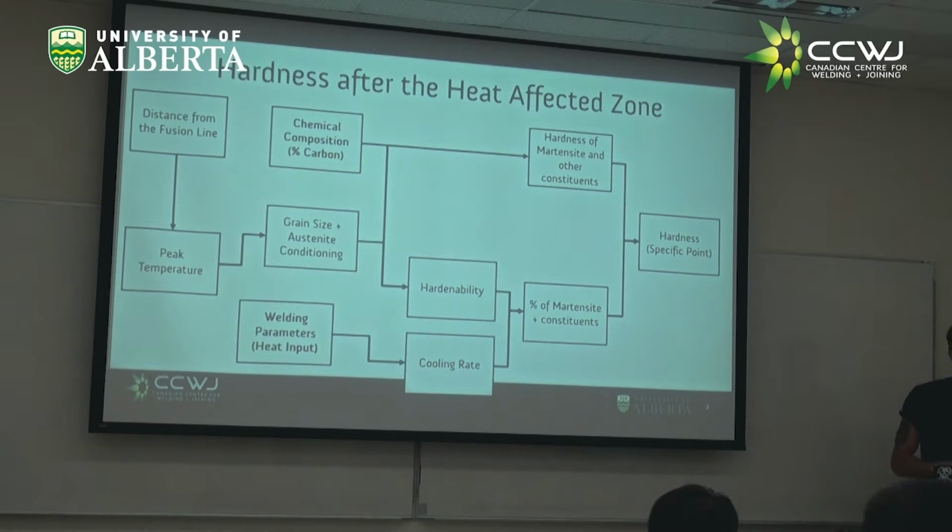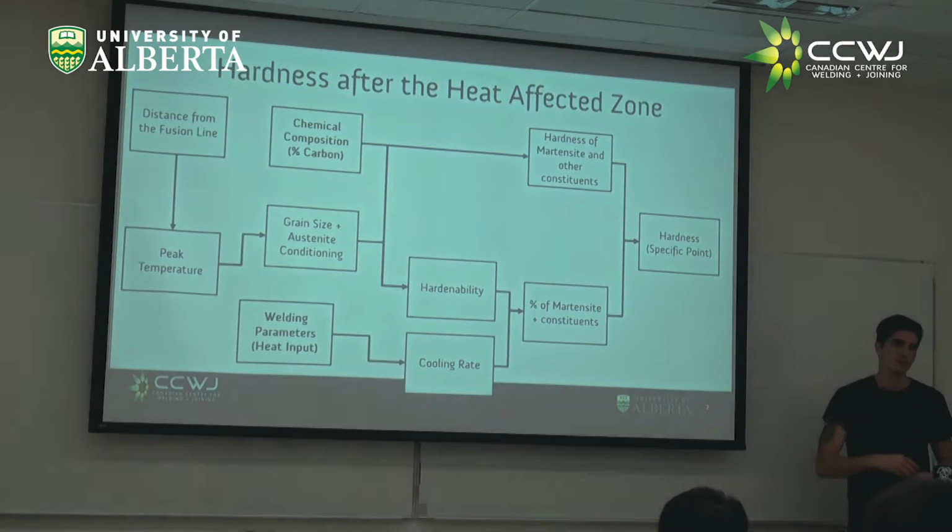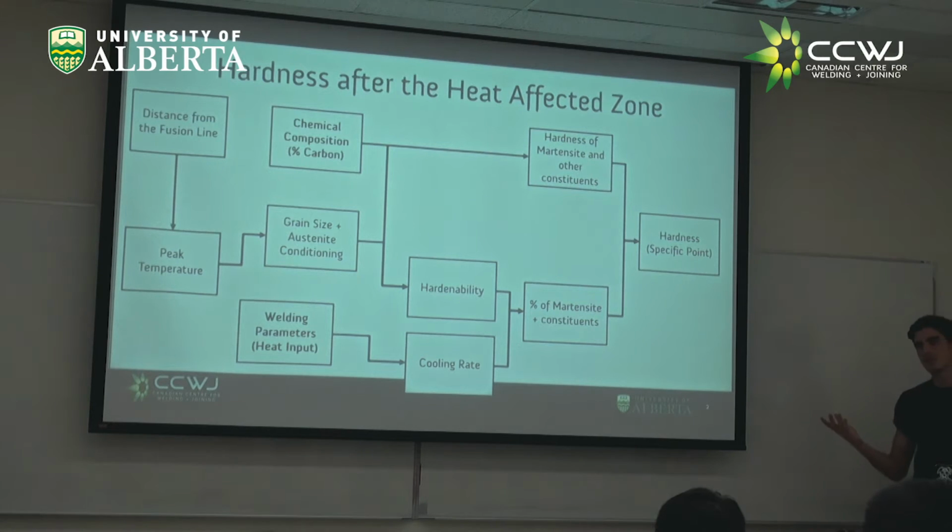Can someone answer that question? Or what does it depend on? Don't read, just answer me. Carbon content? Exactly. Basically carbon content. People will argue that other alloying elements have an influence, especially nitrogen, which behaves like carbon. But honestly, when we are talking about carbon steels, if you don't want to go too deep, it's carbon content.